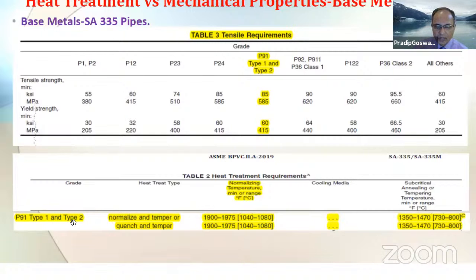The heat treatment for both type 1 and type 2 is normalized and tempered or quenched and tempered. And here you have the normalizing temperature. That means this temperature is for when the material is at the mill stage, the forming stage; for normalizing, the alloys have to be raised to this temperature. After this, they are typically air cooled and tempered later. And if it is quenched, then they have to be liquid quenched. After they undergo normalizing or quenching and tempering, this is the recommended subcritical annealing or subcritical tempering temperature. And you see here, this is 730 to 800 degrees centigrade. That is recommended by the ASME code.